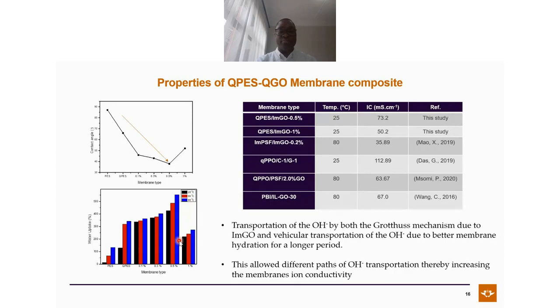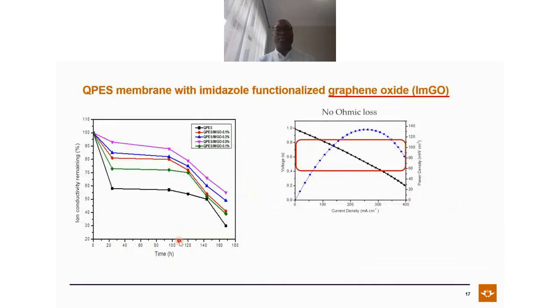Well, when you look at the final part with the degradation of the membrane, what I want you to have a look at is this one. This is a 0.5. You can see that over a 180 hour period, which is 7 days, this material is still able to retain above 60% of its original conductivity. When you look at the membrane without graphene oxide, it's able to retain only 30% after 7 days. So basically, graphene oxide does aid in less degradation.